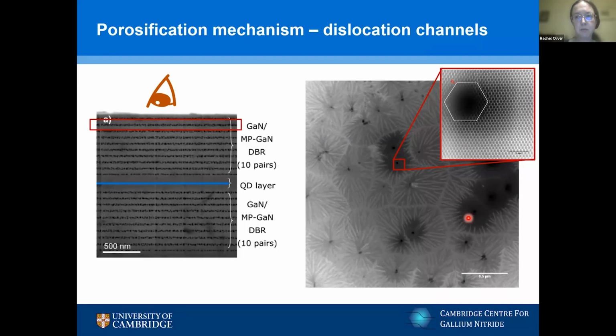We have used an ion milling step to finalize the specimen preparation. I think we've milled away excess material there. We know from other studies that where you have a pre-existing hole or other disturbance in the crystal structure, that can be a section where you more quickly ion mill because the bonds are disturbed and it's easier to knock atoms off. So I think some of what we're seeing here is to do with how we made the sample lookable at in the TEM, not actually to do with the original structure. All of which means that I'm not necessarily 100% sure that the diameter of the pipes we see is exactly what it was in the as-grown pristine material as well. I see, thank you.